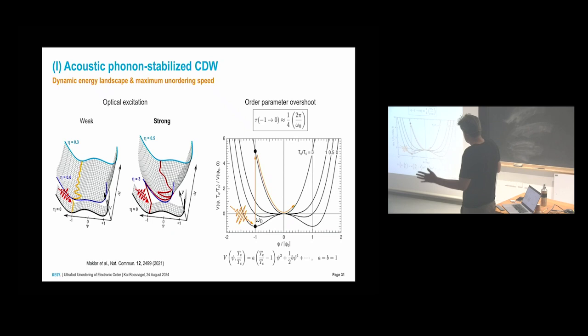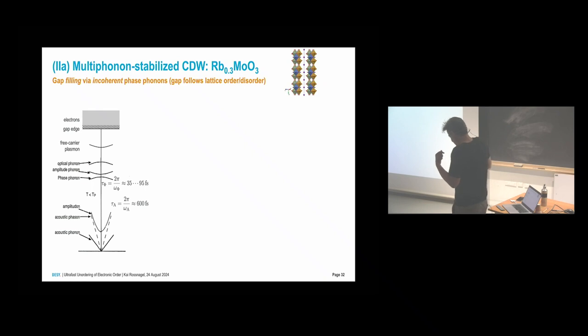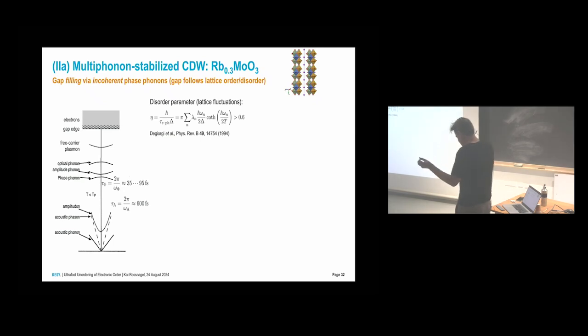So here again, just to illustrate this in a clearer picture, maybe you start here. The order parameter is here, and then it vibrates in this higher state, and again it's a quarter oscillation period in this overshoot regime. So then it can be a little bit more complicated. In these materials, the quasi-one-dimensional charge density wave materials, you also have these phase and amplitude phonons which couple to the gap. And you can also excite those, and these phase phonons in particular can really smear the gap.